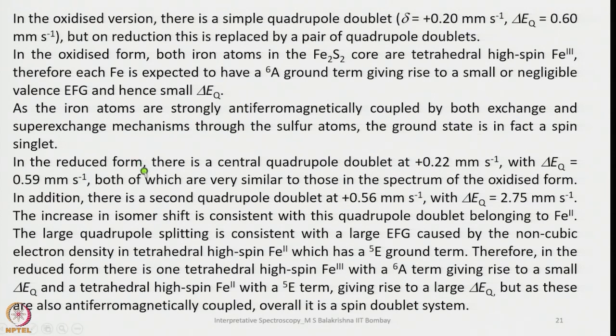So in the reduced form, there is a central quadrupolar doublet at 0.22 millimeters per second with ΔEQ equals 0.59 millimeters per second, both of which are very similar to those in the spectrum of the oxidized form. In addition, there is a second quadrupole doublet at 0.56, considerably larger, with a ΔEQ value of 2.75, whereas it was 0.60 and 0.59 millimeters per second.